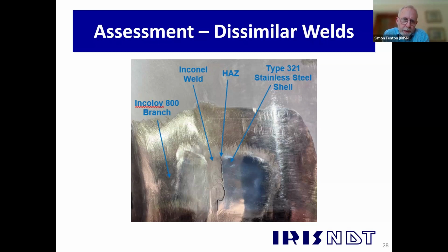So this is one of the branches taking the feed water into this heat exchanger. So we've moved from a carbon steel material on the branch using an Incoloy 800 transition piece. We welded that using Inconel weld to a Type 321 stainless steel shell. So there's quite a few different materials involved in this transition weld. And you can see there that the etch that was carried out using Marble's reagent has formed this very dark line on the microstructure. So that dark line is on the heat affected zone, the fusion boundary between the Inconel weld and the Type 321 stainless.